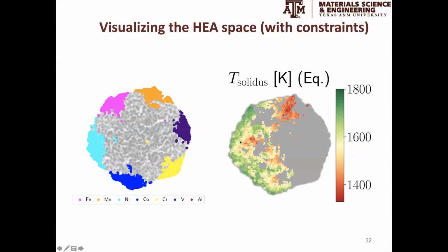This means that, at least in this FCC system, mixing tends to lower the solidus temperature a bit. So there's this compromise: on the one hand, it seems that simpler alloys tend to have higher melting points than more complex alloys. Something I didn't mention is that these calculations were done using the Thermo-Calc high entropy alloy 4 database.